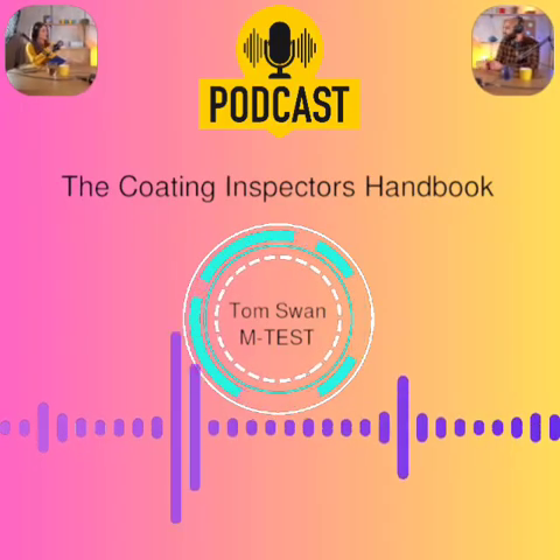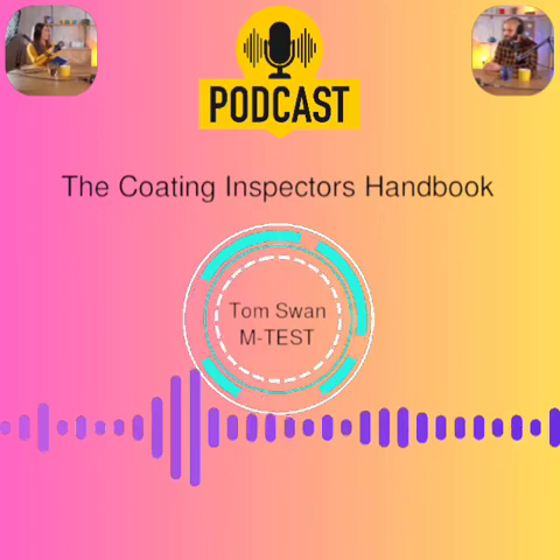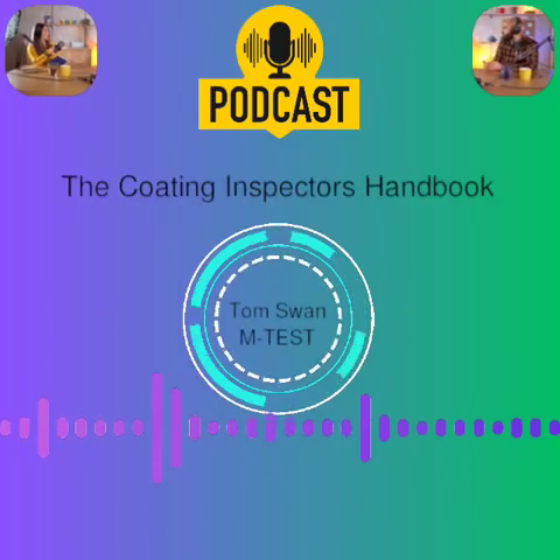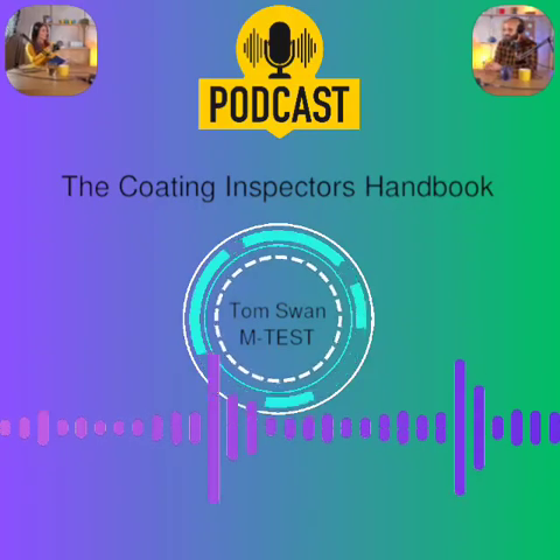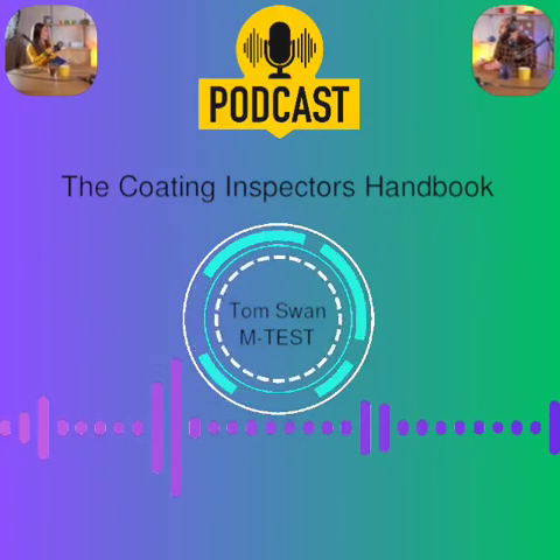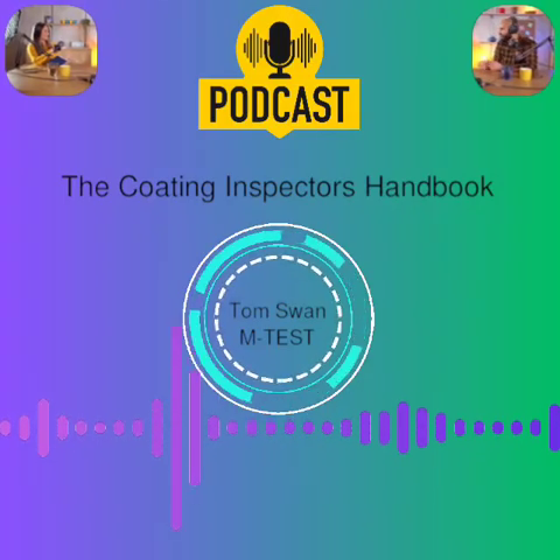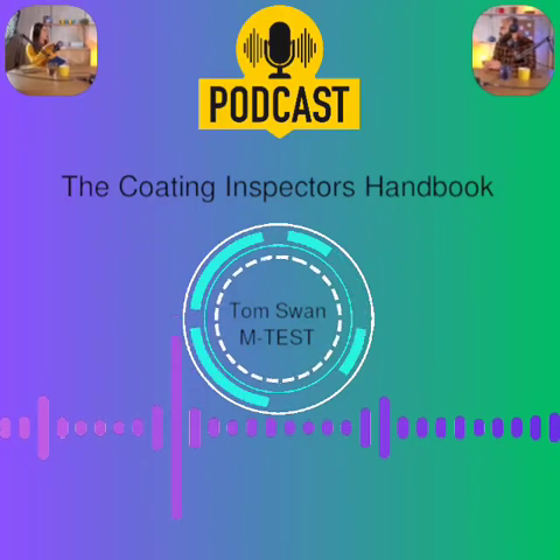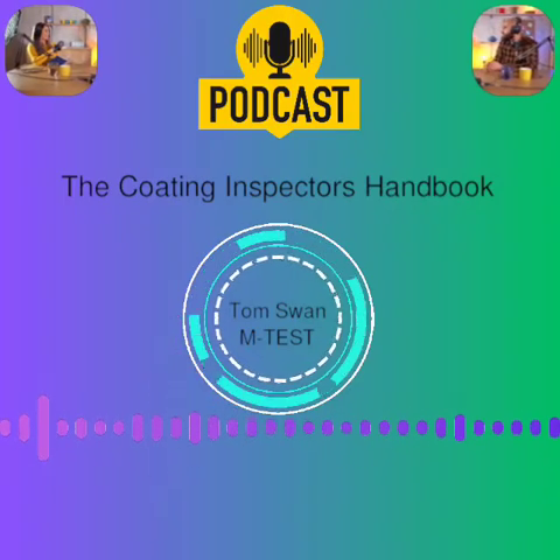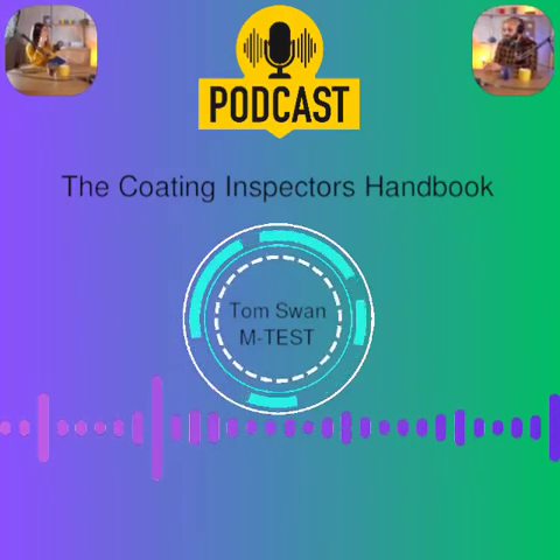Okay, moving from visible dirt to the invisible stuff, salts. Handbook says this is also a primary failure cause. Absolutely. Invisible contaminants, usually soluble salts like chlorides, sulfates, nitrates. And they cause problems how? Two main ways. First, corrosion. Salts act as the electrolyte needed for the corrosion cell to work. Paint is supposed to block that. And then the second way, osmotic blistering.